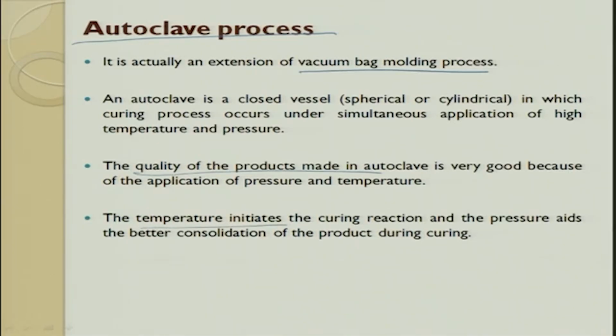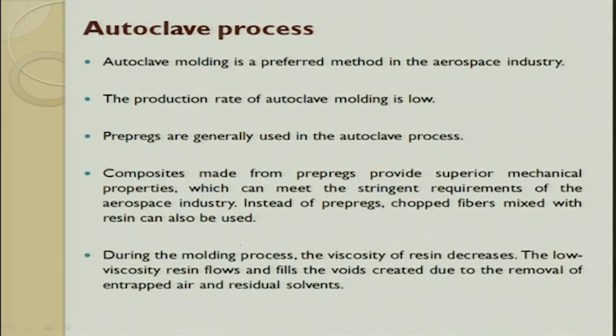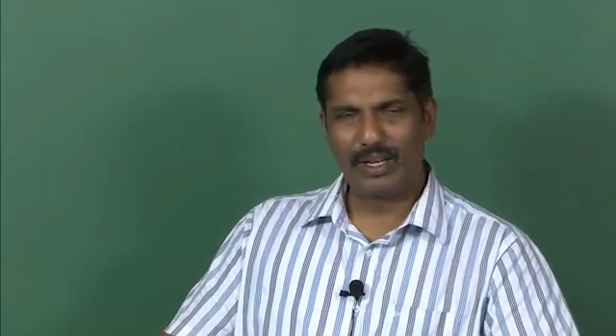The temperature initiates the curing reaction and the pressure aids in consolidation. So I told you pressure, time, temperature plays a very important role in autoclave. Autoclave molding is preferred for aerospace industries, with very low production. It is not like making through hand layup and then coming here. Here we always use a prepreg. So prepreg is glass, the fiber is reinforced and the matrix is wetted and it is consolidated and kept. So we always try to maintain it at a very low temperature so that it does not cure.